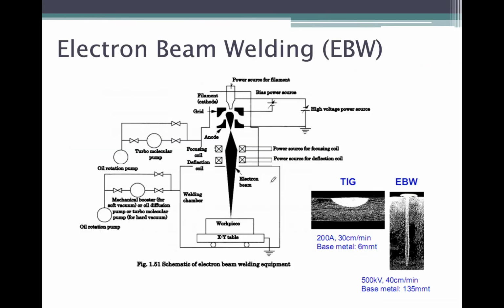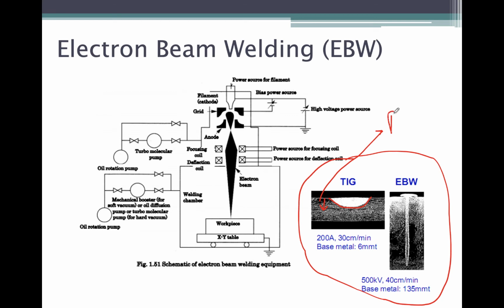So here is basically a diagram of an electron beam welding, and here are the penetration depths of TIG welding and electron beam welding. Here you can see the penetration depth: this distance from the top surface to the maximum weld zone is called penetration depth, PT. You can see that the penetration depth for TIG is quite low, whereas for electron beam welding the penetration depth is very high, and it can do the welding at 40 centimeter per minute.